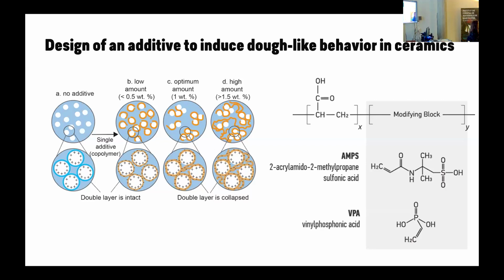So how can you create those systems if you coagulate the particles together, but homogeneously, because otherwise the water will get out, and it's called bleeding. You don't want some of the ceramics to settle here and then see water in the system. That is also a common problem in cement rheology. So what we have created is a polymer that has an ionic backbone. With that ionic backbone, we can cover these particles with a monolayer, and if a single polymer is bridging among a couple of particles, then you see this homogeneous coagulation effect. In this paper and others, we modify the ionic behavior of the system. How you modify it is by introducing different types of monomers to modify polyacrylic acid. And then you create this adsorption behavior in this type of polymers.